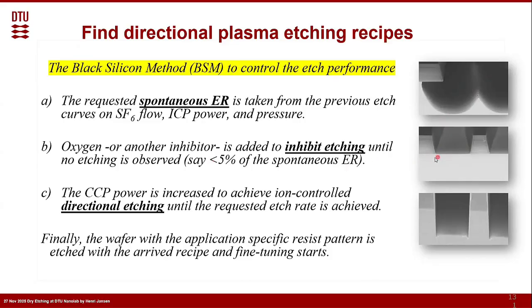Let's say below 5%. So what would you see like this? And now we switch on the CCP power. So here we did the etching with, let's say, the ICP power. So that one is generating the radicals, but no DC bias, as we remember from the previous lecture. And now we add the CCP power, so that's the platen power, to extract the ions from the plasma generated by the coil power. And they will knock away the inhibitor, and after sufficient power, in the beginning maybe it's hesitating, but then you will see that you come back to the original etch rate at the bottom, and that's where we hit our maximum performance. As easy as it is.